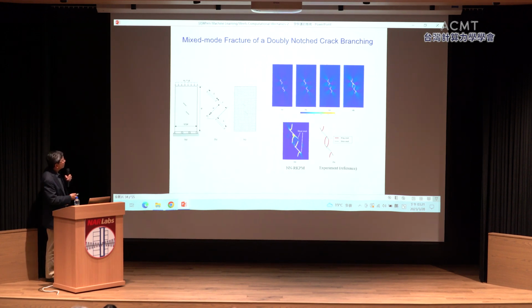We also use this, for example, to model more complex fracture patterns. And again, the background grid for the reproducing kernel is fixed, just like this. But as the crack grows, the neural network will capture that. And this is a comparison with the experiment.